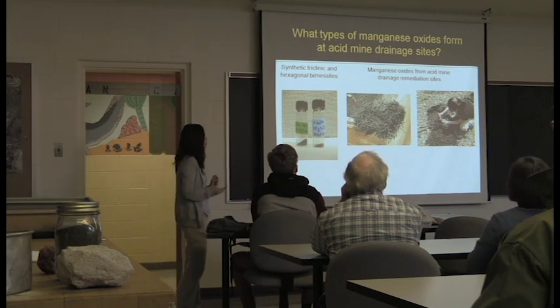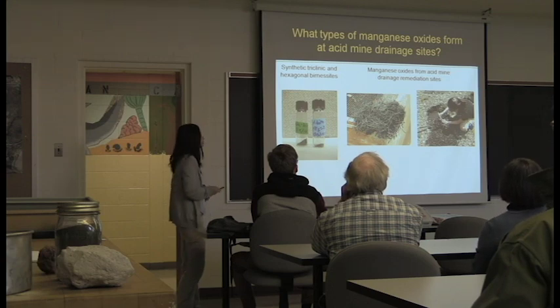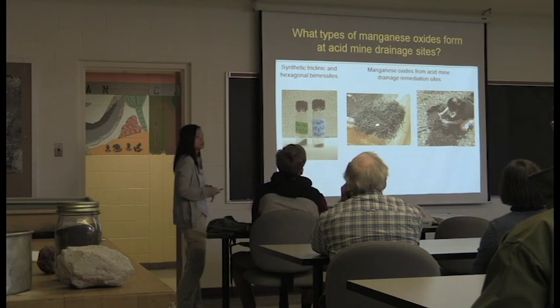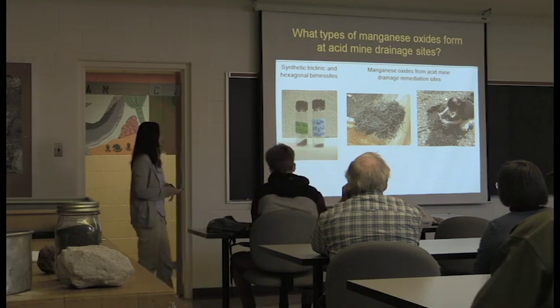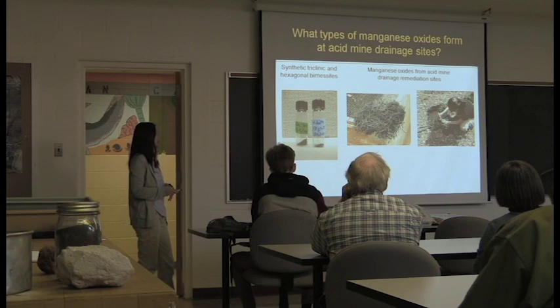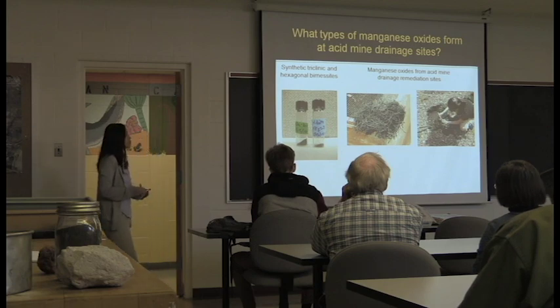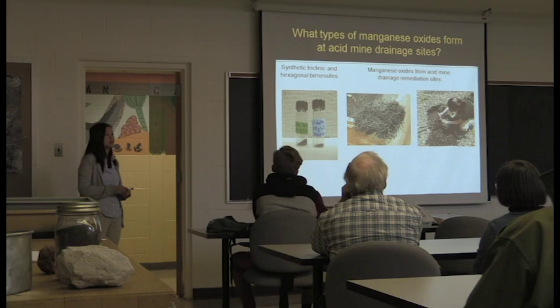And then I also collected a bunch of manganese oxides from acid mine drainage sites. This is a sample from a metal removal unit, and all this stringy stuff is the coconut coir that's in it, and it's black from the manganese oxide coating. And over here is some manganese oxide from a manganese removal bed. And so you see I've dug a hole and the water is black due to the manganese oxide. And so I collected some of the limestone pieces that were coated with the manganese oxide.